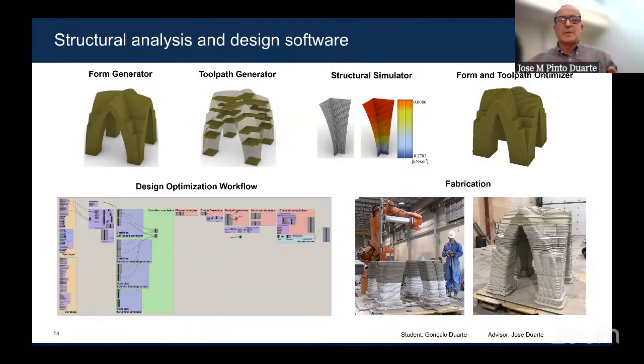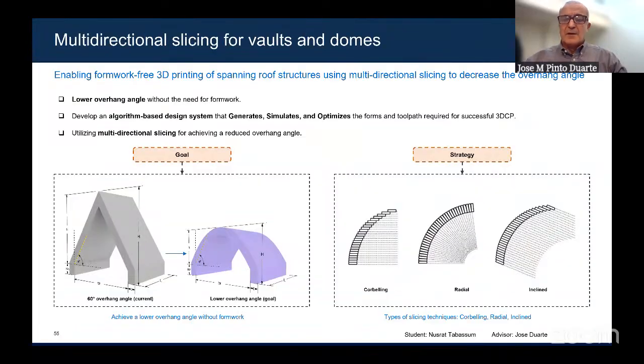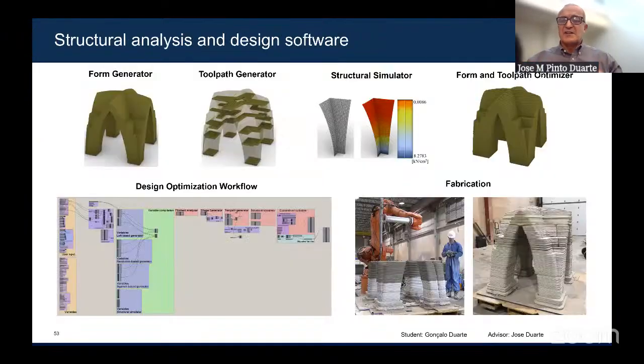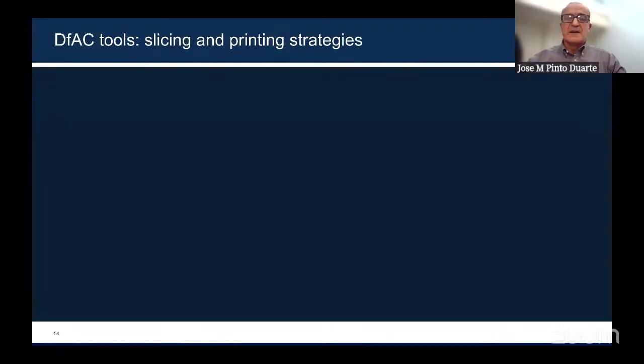So basically, what you do is generate the overall shape of the part, develop the tool path, do structural simulation during the printing, and then use optimization to find out what's the best tool path design. And best in this case means avoiding collapse and, at the same time, decreasing the use of material, and therefore decreasing the time of printing. As you can see, in this case, the vault still uses a lot of material, and it's still very steep. So we are trying to find ways to decrease the angle so we can print vaults that are shallower. And that's exactly what we're doing.